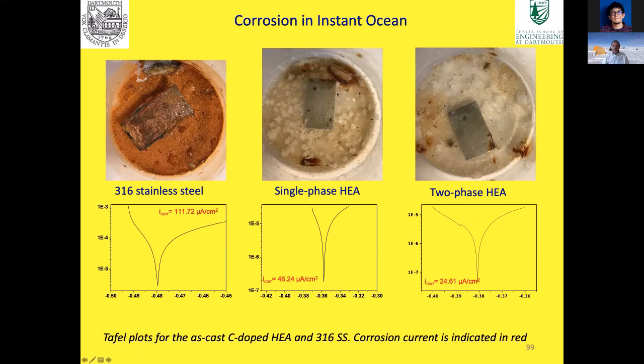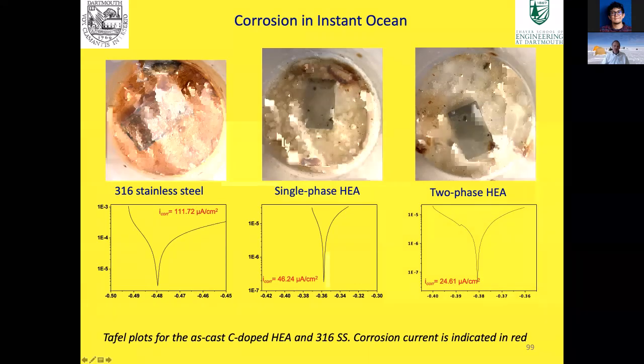And you can see that I just let the water evaporate from these, and the high entropy alloy has hardly gone rusty at all, whereas the stainless steel has a tremendous amount of rust, and all this brown here is the corrosion products. This is a little unfair test on stainless steel, because stainless steel is well known to be susceptible to chloride attack.